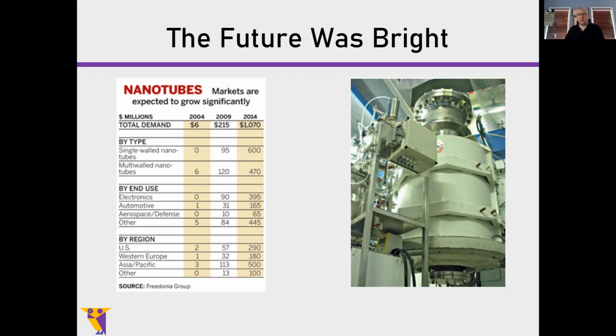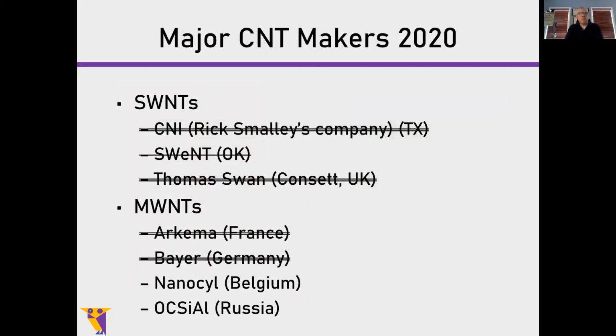And what you see on the right is an Arkema nanotube reactor capable of making about 30 metric tons. When it made 30 metric tons, Bayer decided that they had to up them, so they went to 60. Arkema decided they needed to improve it, so they went to 80. Bayer wasn't standing still for that, so they went to 200, and Arkema went to 400 metric tons, eventually being able to produce that many multi-wall nanotubes. There was only one problem.